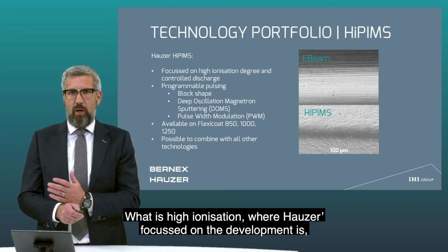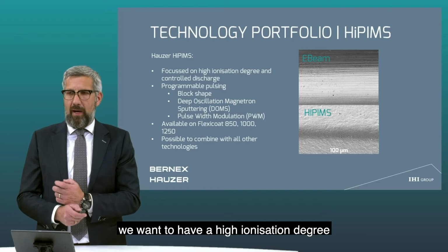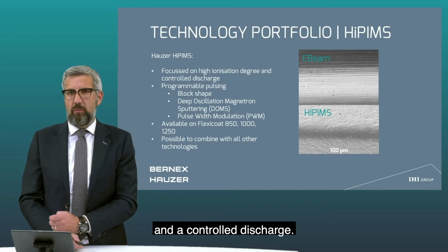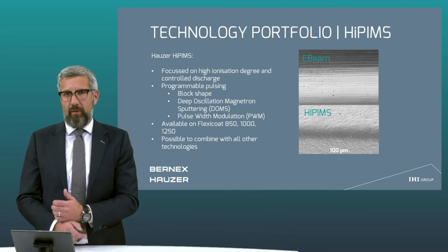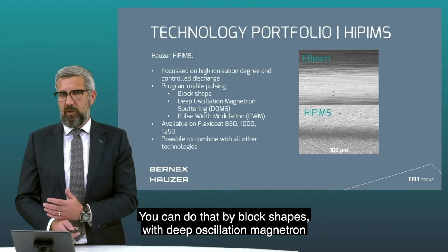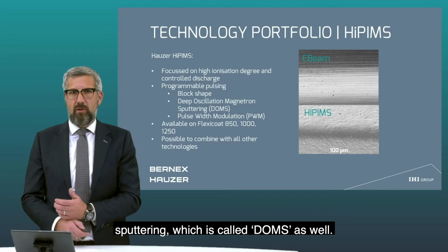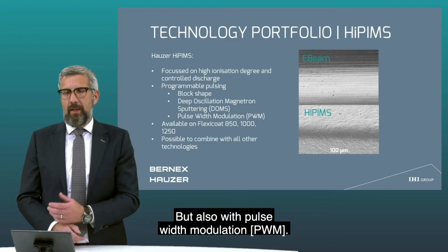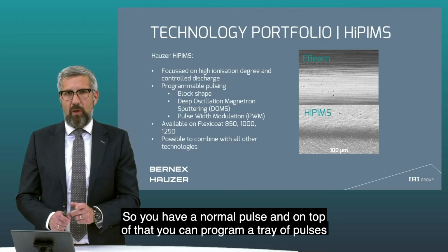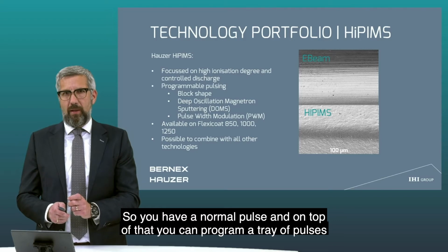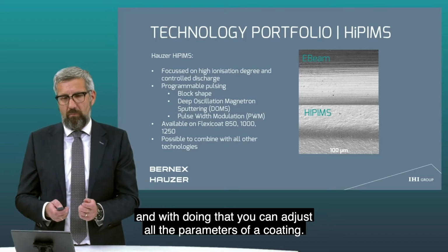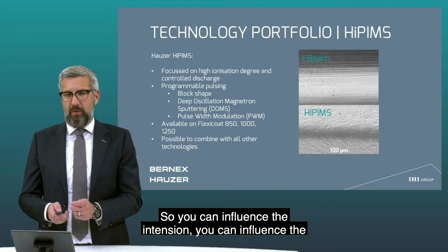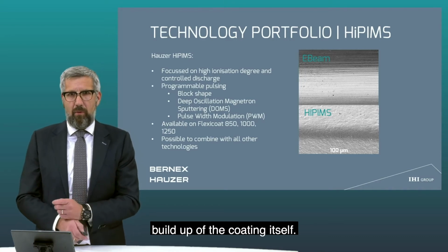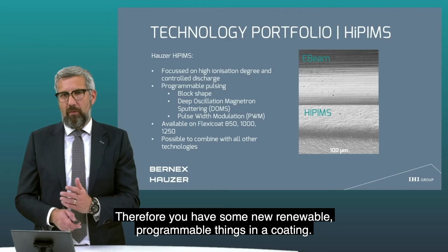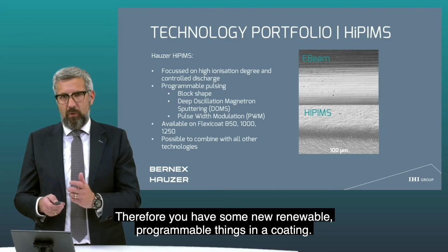Where Hauzer focused on the development is that we want to have a high ionization degree and a controlled discharge, meaning that the sputter rate still stays high. You do this by programmable pulsing, and you can do that with block shapes, with deep oscillation magnetron sputtering, called DOMS as well, but also with pulse width modulation. Pulse width modulation needs a little bit more explanation. You have your pulse, the normal pulse, and on top of that, you can program a train of pulses, and by doing that, you can adjust all the parameters of a coating. So you can influence the internal tension, you can influence the build-up of the coating itself, and therefore have some new, renewable, programmable things put in a coating.